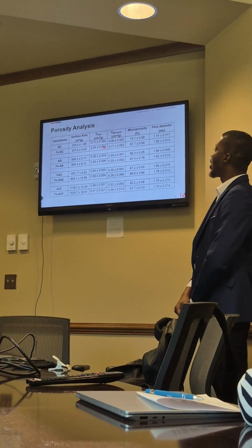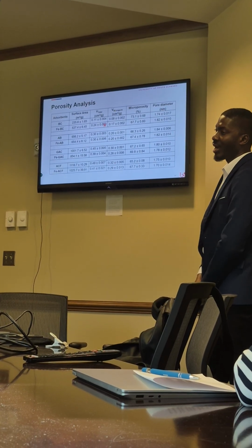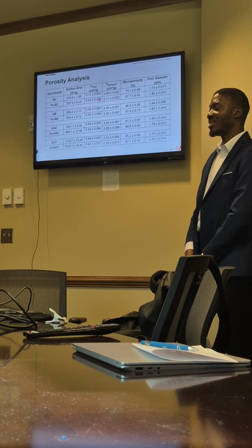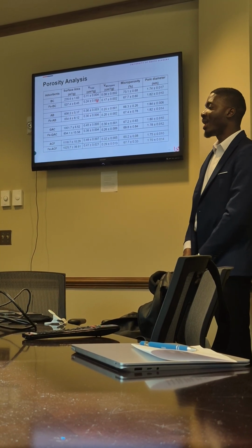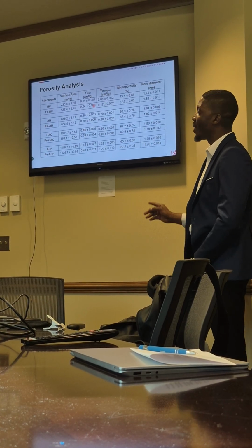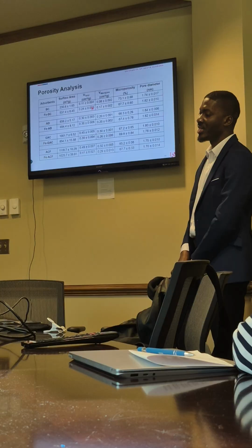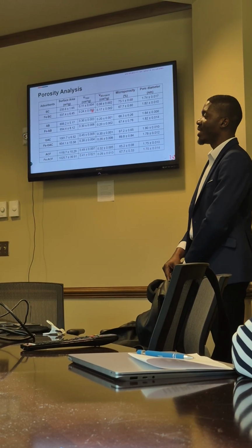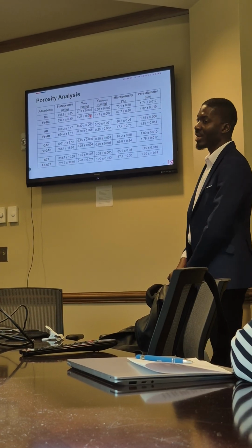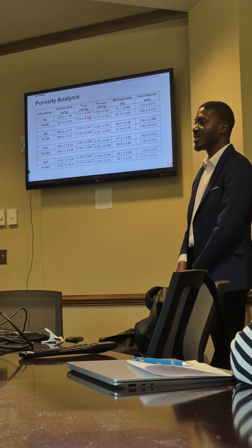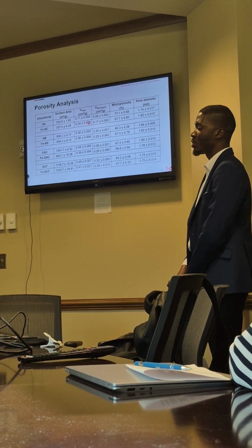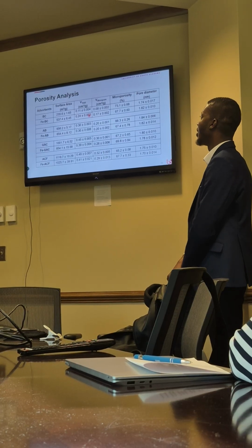So we're trying to understand why this increase happened, and current studies have shown that iron chloride is now being used as an activating agent to chemically activate carbon adsorbents. And we can also say that our biochar underwent chemical activation after ion attachment because of the heat treatments that we also took. And secondly, our biochar had volatile matter present, about 16%, which meant that all that volatile matter could have been lost to also open up the pores of the material, which we can see in its surface area and micropore volume.